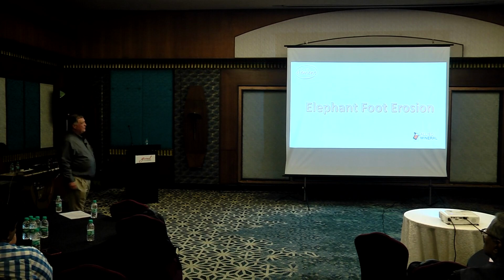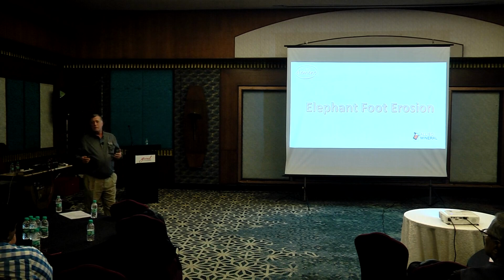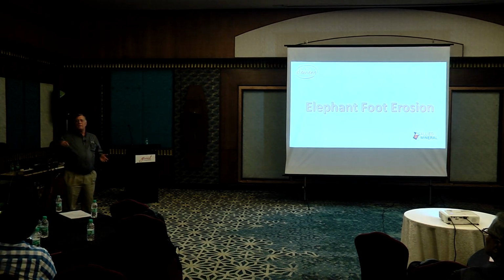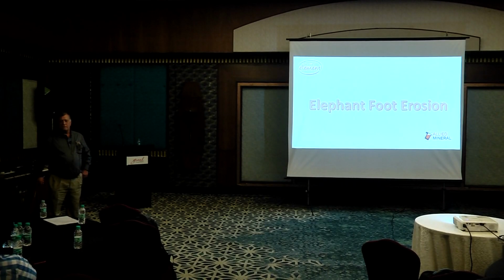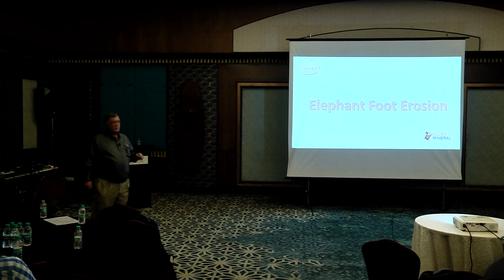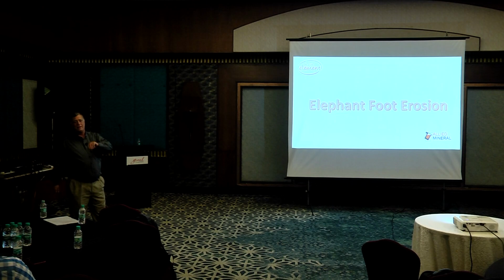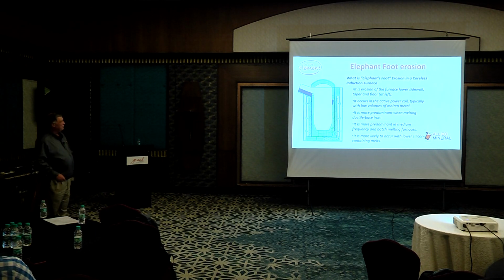Everybody's like, how can we eliminate elephant foot? In a lot of cases, you cannot. You can't eliminate it, okay? It just happens. But what you can do is slow down the rate of erosion. You get a lot of stirring action in that taper section and floor, lots of it. You get a lot of mechanical abuse. All of this happens, and there are a lot of chemistry variations that are typically happening. So the best you can hope for in most cases is that you push it to get more lining life, but you're never going to be able to eliminate it completely.